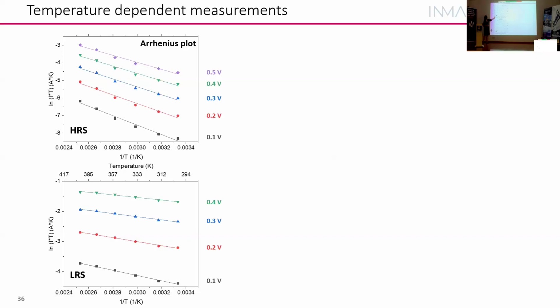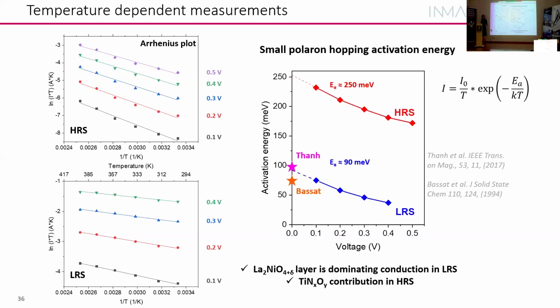Okay, now we did these plots of the current, that would be the same as conductivity, versus the inverse of the temperature. For the different points we have measured at different voltages. And from here, we can extract an activation energy. So we have the activation energy from the low and from the high resistance state. From the low resistance state, we could extrapolate to the activation energy at 0 volts.